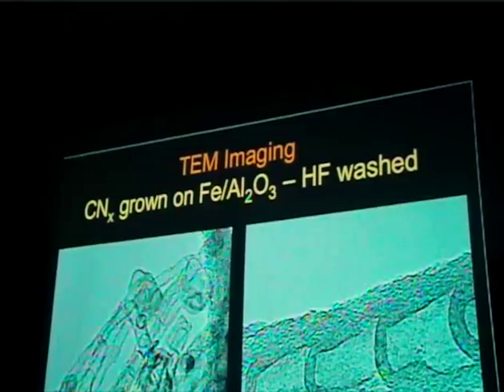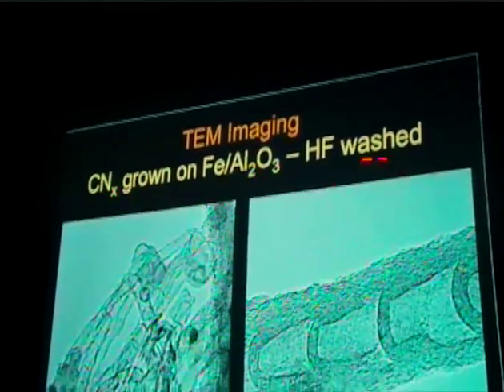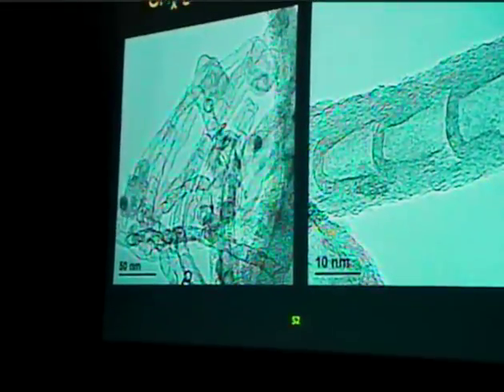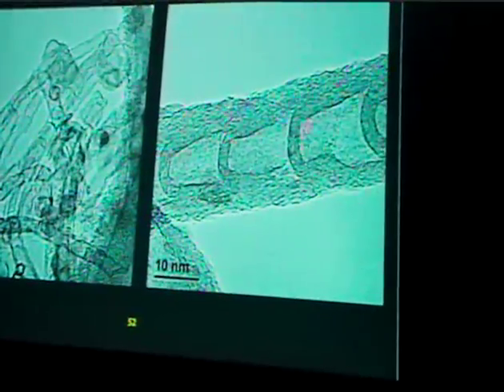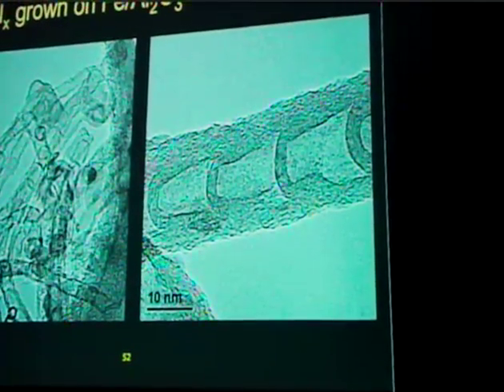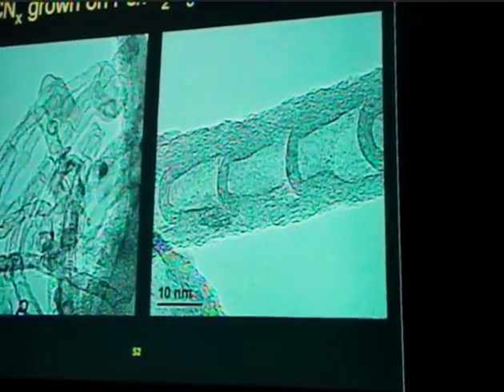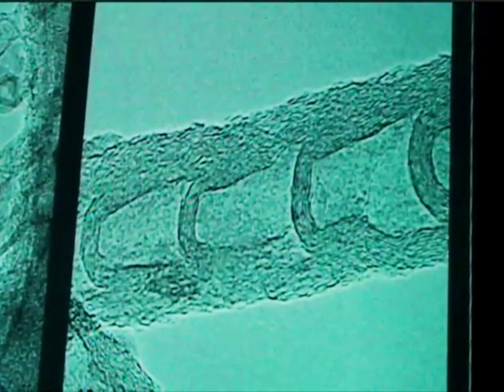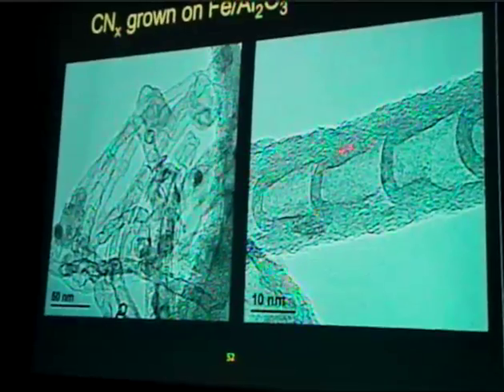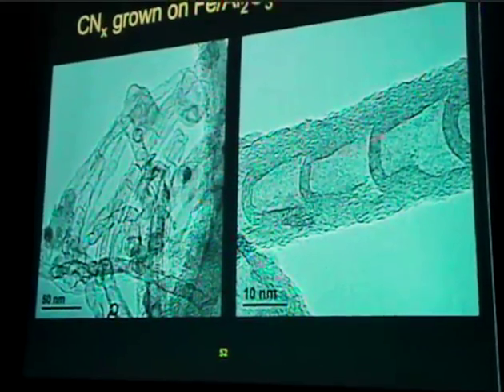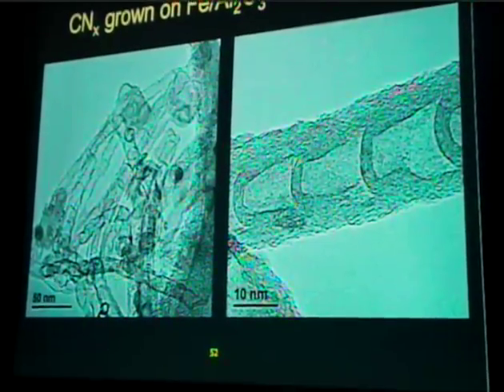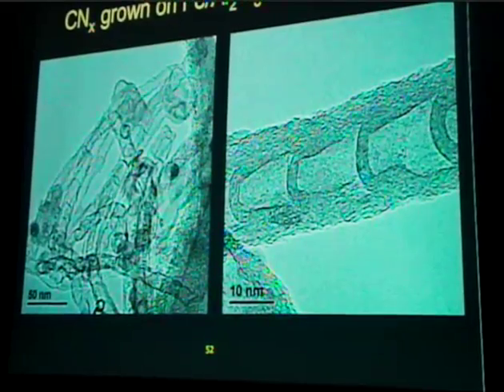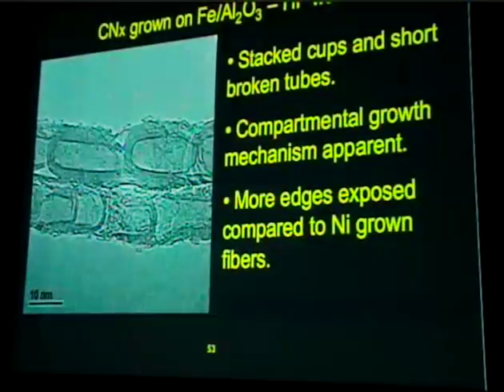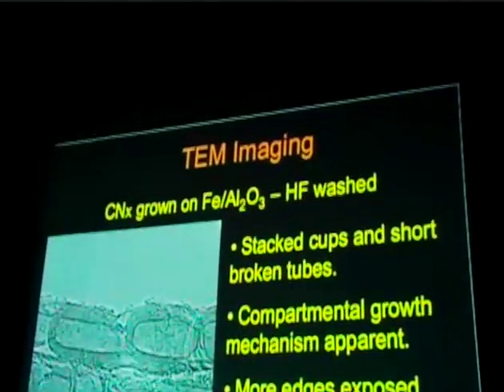If we look at CNX materials grown on iron-containing alumina, again, this is after hydrofluoric acid washing, we see what we call a stacked-cup structure. It's a compartmentalized growth, and if you look closely, the graphite planes are ending at an angle to the main axis, exposing mostly the edge planes of the graphite. Again, this is a closer look.